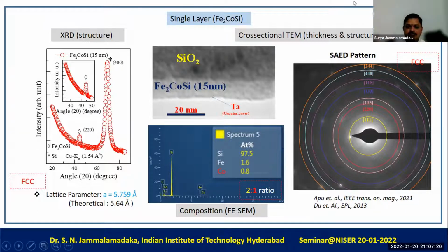Yeah, we don't see any epitaxial nature because we do see many peaks, many HKL values over here. So it is probably polycrystalline, although in X-ray you are getting only one peak. Yeah, one peak. It might be polycrystalline. I agree with you. Yeah.